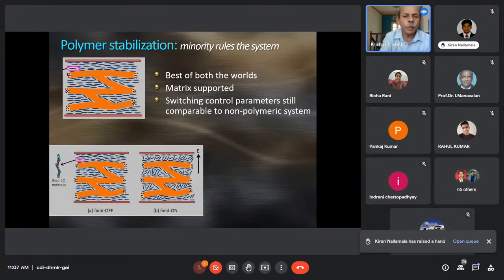I still have the polymer, which is going to make it a self-supporting system. The matrix supports the liquid crystal, and I still have the switching advantages of creating scattering in these systems, and so appeal to the PDLC characteristics of having pure refractive index and not the birefringence of the native liquid crystal come into the picture. That's why people are working on polymer stabilized systems. Here, the minority, which is the polymer, can control the way the liquid crystal majority molecules operate in the systems.